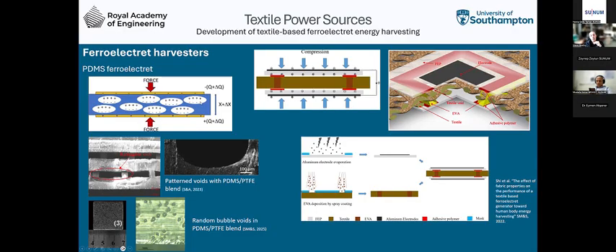So each void becomes an individual electric field across it. And if you apply a force and these voids change shape, you change the electric field accordingly, and you get a net flow of charge, a net voltage output. So they look just like a sort of piezoelectric material. If you squash it, you get charge output and you get a voltage signal, etc. But the mechanism is very different to piezoelectricity.